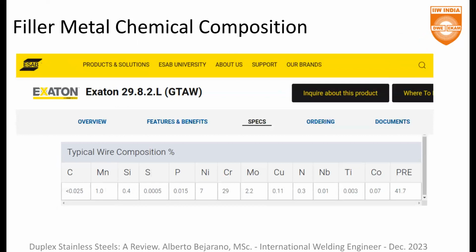Nickel 7%, high percentage. And PRE 41.7. This is the PRE of the filler metal. This is very important to be understood. This is related with the filler metal, not related with the weld metal.